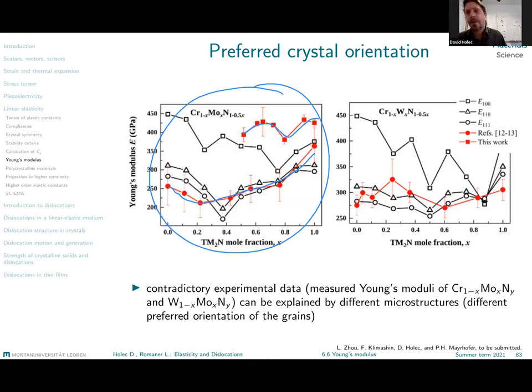experimental measurements of indentation modulus for chromium molybdenum nitride. And if you look just at one fixed composition here, we see that the experimental values can represent a large scatter of values, right? We can get really a very large difference in the measured value. Here it's something around 250 and close to 400 GPa. At first sight, you might say that your experiment is that inaccurate, but that would be too bad.